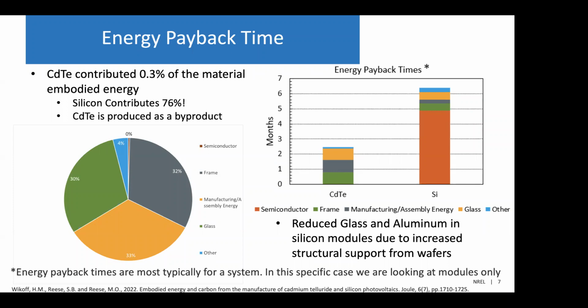But we do understand typically this is more of a system sort of equation. But if you read through a lot of different papers, a lot of people report on an energy payback time of modules alone. So what we found is that the energy payback time of a CadTel module is about 2.5 months. What does this mean? That means that you make this module, you get it out in the field, and after the first 2.5 months, it is basically just generating the energy that had been necessary and consumed in order to manufacture it. That means for the next 29 years, 8 months, and 15 days, all the energy it generates is excess of what it had taken to manufacture it. A silicon module took closer to about 6 1/3 months to have an energy payback.